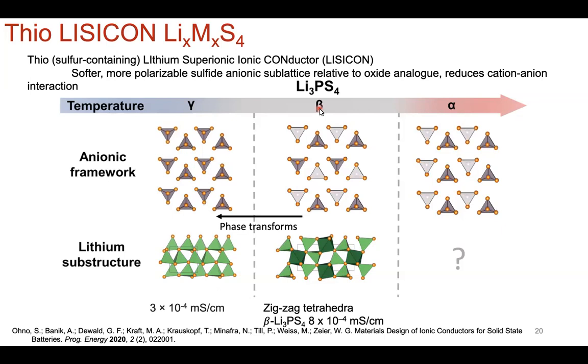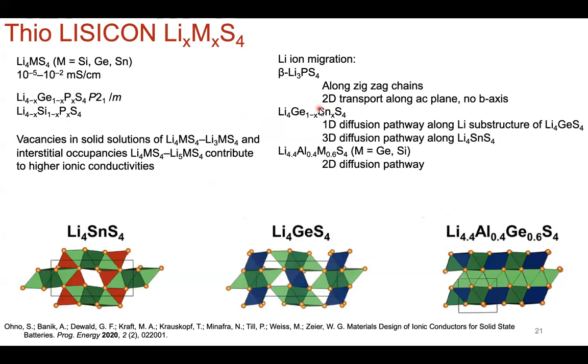And one of the reasons, on top of this being really cool, interesting materials science and materials chemistry, is that by accessing these phases that you wouldn't normally get in the bulk phase, you can now have access to lithium ion migration pathways that you didn't have before. And the more you understand how these ions migrate, the better you are at building your fundamental toolset and theories for how to increase the intrinsic properties like ionic conductivity. Okay, so there's my little spiel about why synthesis is necessary.